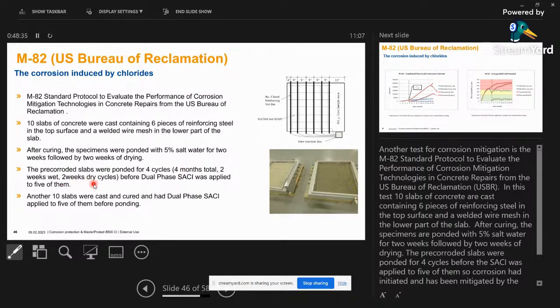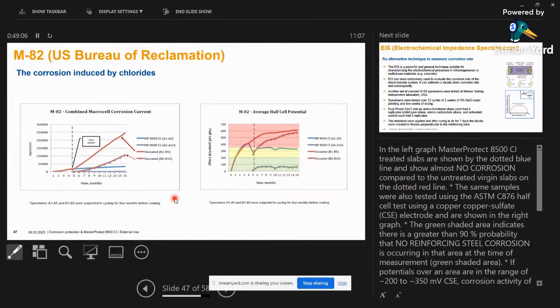So you see, the alternate wetting and drying of these reinforced concrete specimens was done with a primary objective, because when you have alternate wetting and drying, there is a lot of ingress of chloride. So that was to create an atmosphere where the concrete specimens get more and more infused with chloride ions, so that the condition can become much more severe. And that is when the whole thing was then assessed and measured as to how it has actually performed.